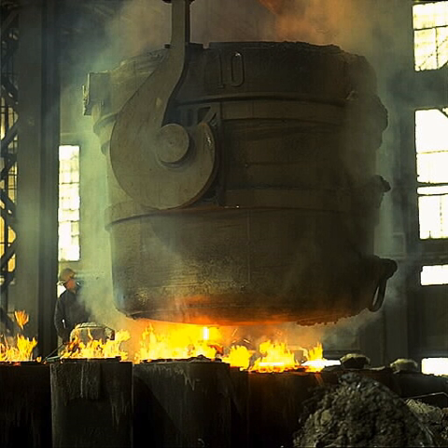Tungsten slows the formation of cementite, keeping carbon in the iron matrix and allowing martensite to preferentially form at slower quench rates, resulting in high-speed steel. On the other hand, sulfur, nitrogen, and phosphorus are considered contaminants that make steel more brittle and are removed from the steel melt during processing.